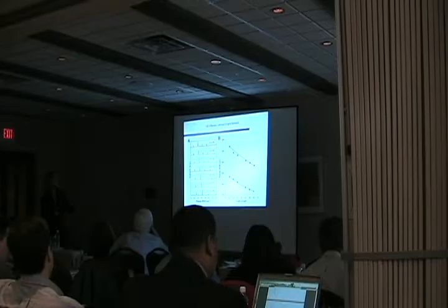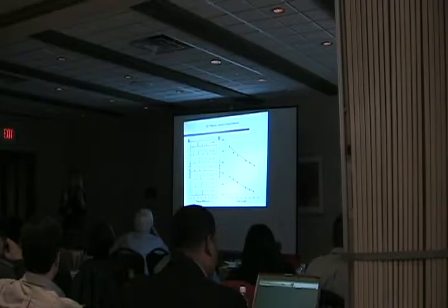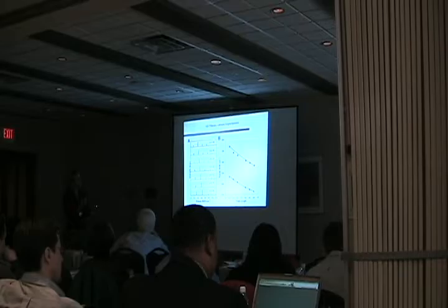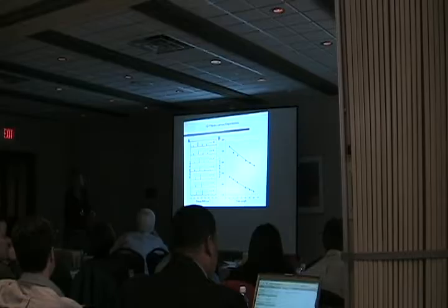and that's going to modulate its resonant frequency. This shows several of the LAM modes that are supported by an alkane chain, which correspond to the number of nodes of the molecule. These are the longitudinal displacements. This is all a 1D model. But if we take a 1D model that couples the LAM modes to the gold sulfur stretch and compare this to the regression we saw experimentally, we see a really beautiful agreement with why this mass dependence is there. So in a simple 1D system, we can see that the actual molecular motion couples very cleanly to the gold sulfur stretch. That's undoubtedly a general mechanism that should have some effect on virtually any molecule